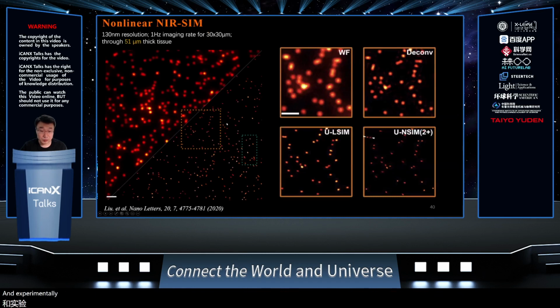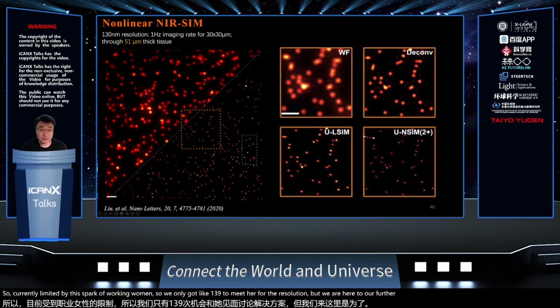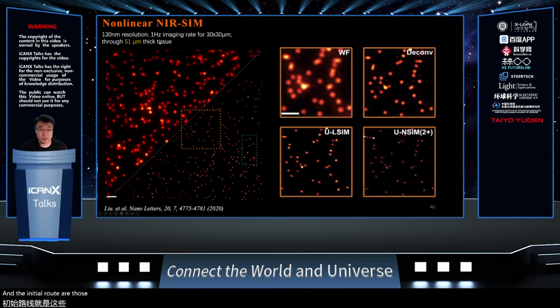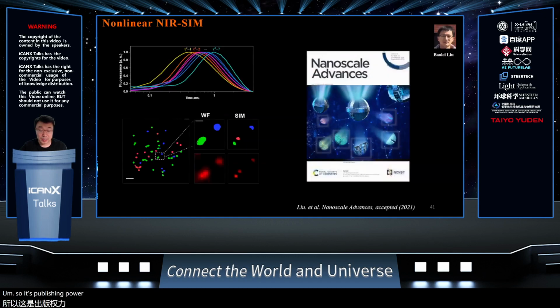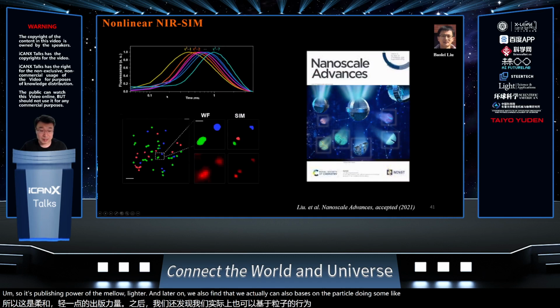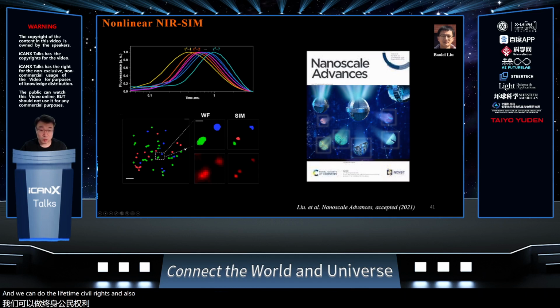And experimentally, we did that. We put the nanoparticles inside and we can do the nonlinear imaging. Currently, limited by the working wavelength, we only got about 130 nanometers of resolution, but we are trying to further enhance this. And for the imaging, we got almost video rate, like 1 Hertz, so we can see some dynamics using this super-resolution. It was published as a cover of Nano Letters. Later on, we also found that, based on this particle, we can do some multiplexing, because we can tune the lifetime. If we shift the lifetime, we can do lifetime super-resolution, and we also have different colors, so we have a 2-dimensional matrix.